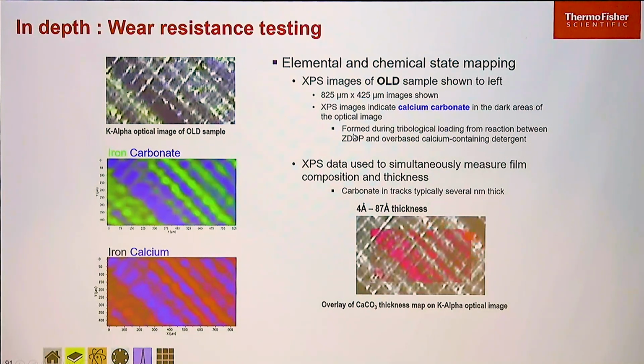We can also measure the thickness of the calcium carbonate because it's thin enough that we can see the substrate signal underneath it. By using the software to calculate how much the signal from the substrate is attenuated by the overlayer, we're able to calculate the thickness of the overlayer. In this case, we've got the calcium carbonate, we know its density, we know its electronic properties, and we look at the signal from our iron, and we know its kinetic energy, so we know how easily it will transfer through a material as dense as calcium carbonate, and we can use that to calculate the thickness. So we can see it varies from 4 angstroms to 87 angstroms,